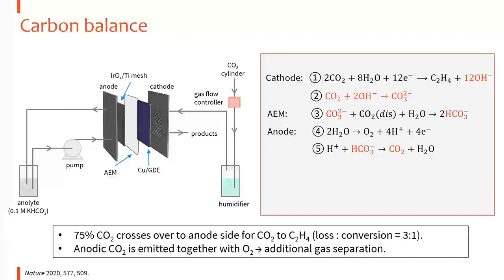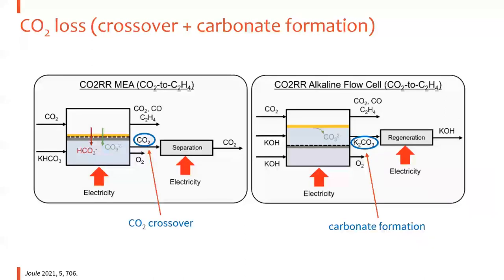So if we do further calculation, we found that 75% of CO2 will actually go the crossover way to the anode side. That means at most only 25% of CO2 will be converted to the final product we want. And also the CO2 at the anode side will be a mixture with oxygen. That means if we want to recycle the CO2 back to the cathode, we need to pay some extra cost for the gas separation. This is what we call the CO2 crossover and carbonate formation problem.